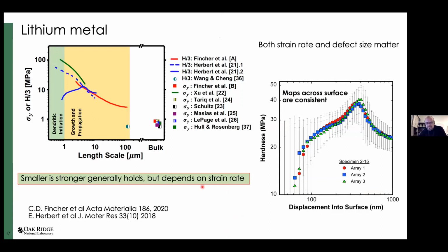Right. So the length scale shown here is of interest in terms of the surface defects that you encounter on the surface of solid electrolytes. So this tells you that the processing of your solid electrolyte needs to be pretty much impeccable, so you don't have any voids or grain junctions that create defects of just the right size, so that lithium will create high pressure in it. It does not affect the form factor of the battery itself. It's density and size of the interfacial defects in the electrolyte.